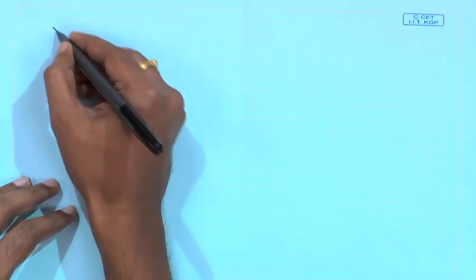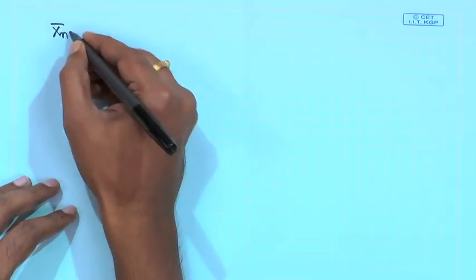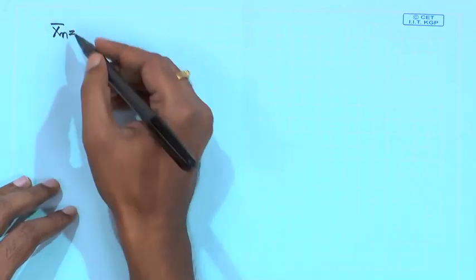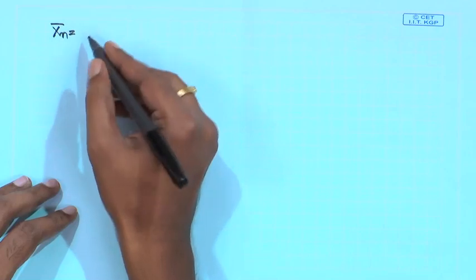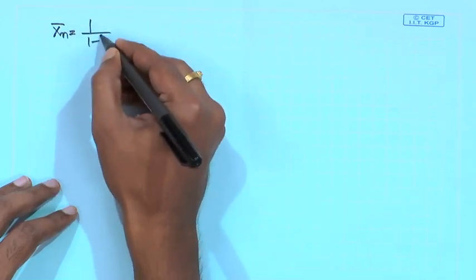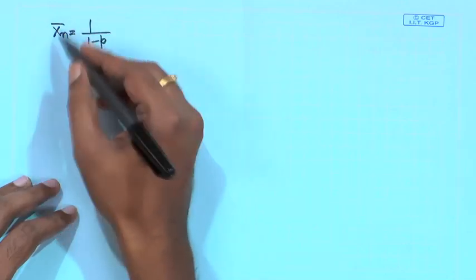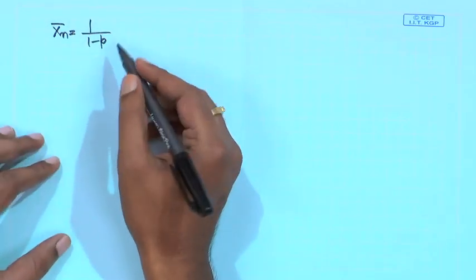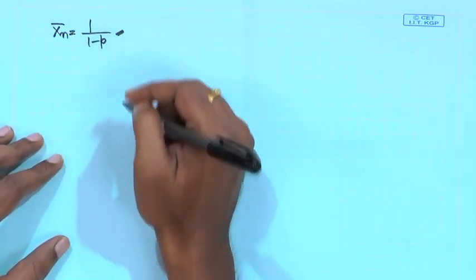In this case we are taking polyesterification as an example. So, let us go back to the derivation right where we left it. We had actually derived an expression for xn bar, which is the number average degree of polymerization, and this was equal to 1 divided by 1 minus p. Now, this particular expression is valid when you have stoichiometric amount of starting materials. So, this is your Carothers equation.